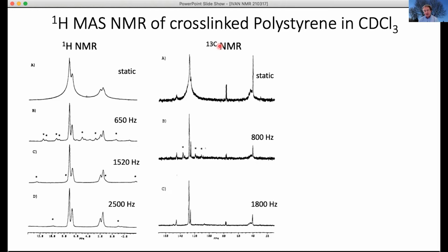When you spin fast enough, about 1 or 2 kilohertz for us, you spin out dipolar couplings. You artificially make the environment isotropic, so solution-like. In solution, small molecules and even linear polymers can tumble so there is no average contribution from particular neighbors with dipole moments, protons that couple to your proton of interest.